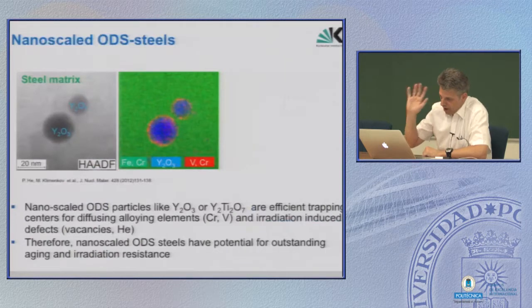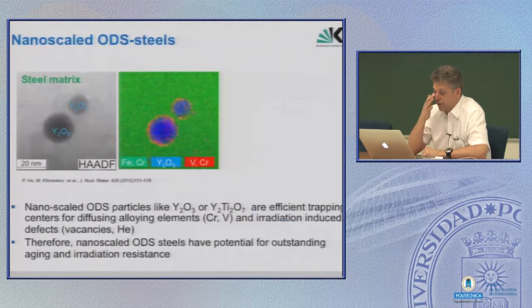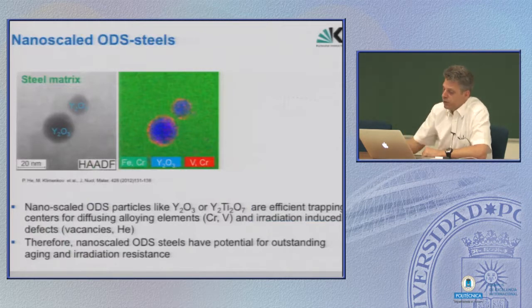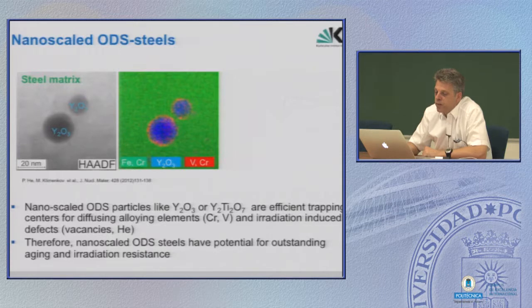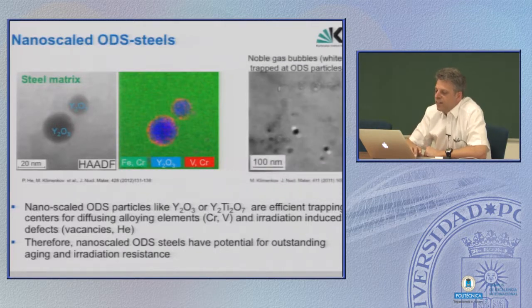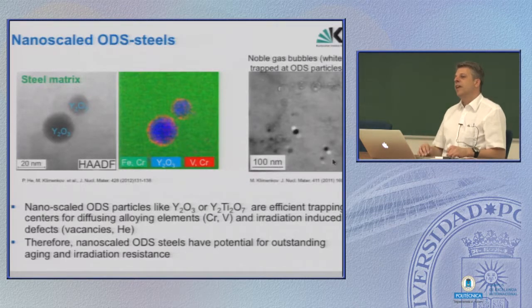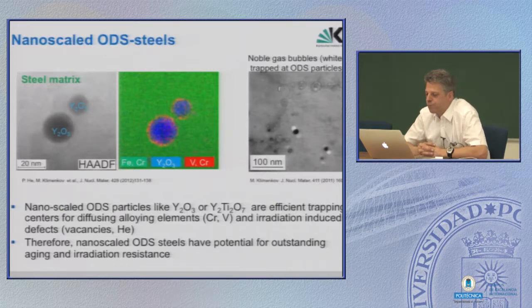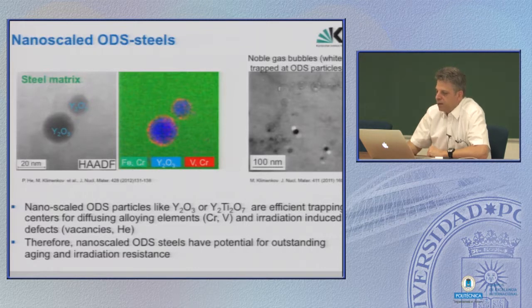I could spend hours alone on this topic. There are thousands of publications already. In principle, you see it here, fine dispersed oxides are produced on a powder metallurgic way in these steels. And the result is that helium or any gas bubbles are trapped to these fine precipitates. They will not be able to grow to produce this fracture behavior at grain boundaries. And well, at the moment, it looks like that this is the only way for the far future to overcome the problem.